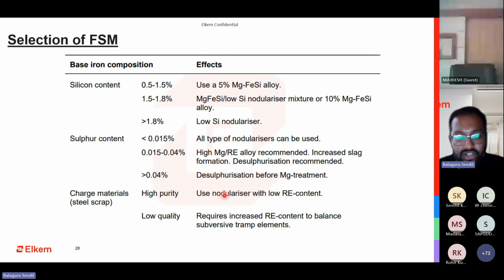So if you're using high purity charge material, you will not have a lot of trace elements: titanium, chromium, vanadium. You can calculate how much are those in your day-to-day foundry. There's something called Thielmann's factor. You can Google that and get that value and see whether it is above 1, less than 1, or equal to 1. So that will give you an idea.